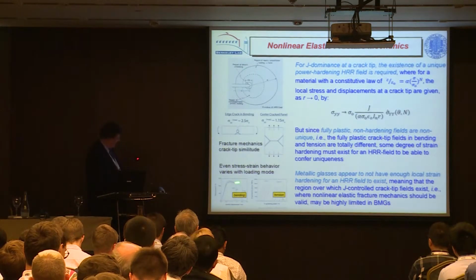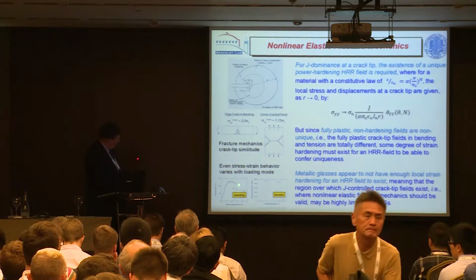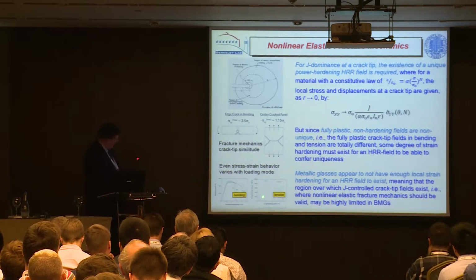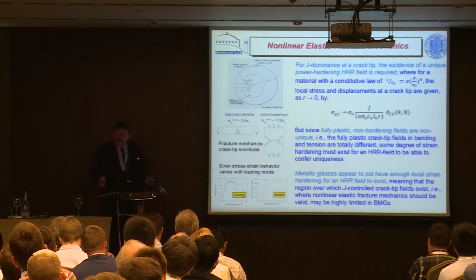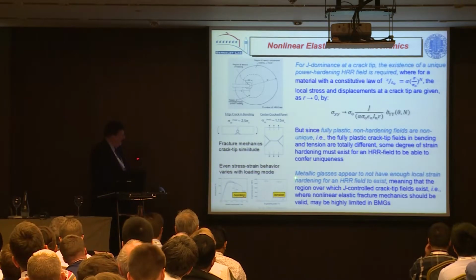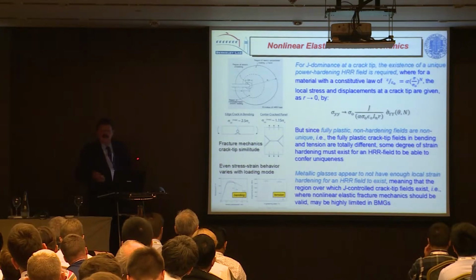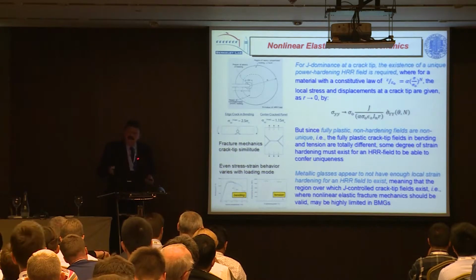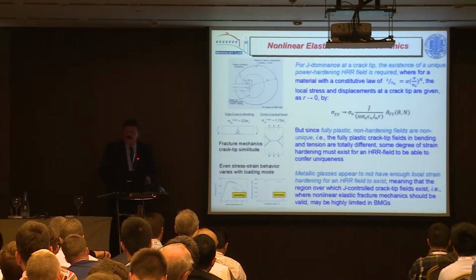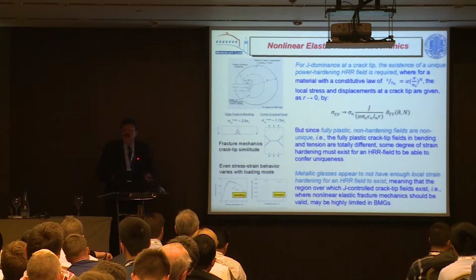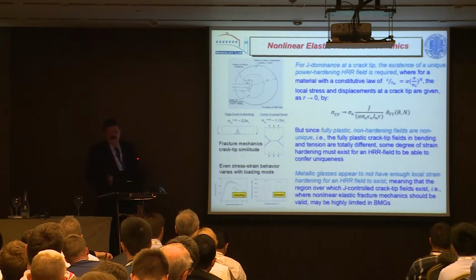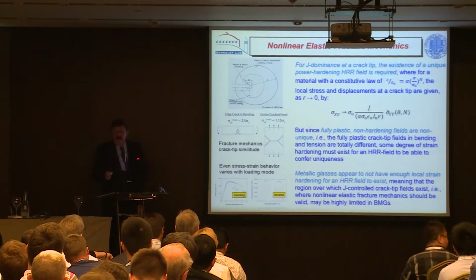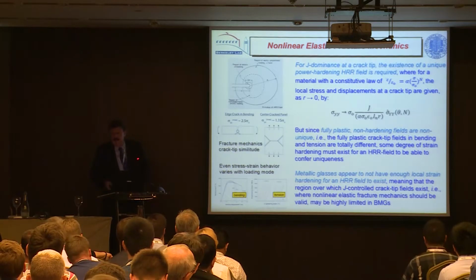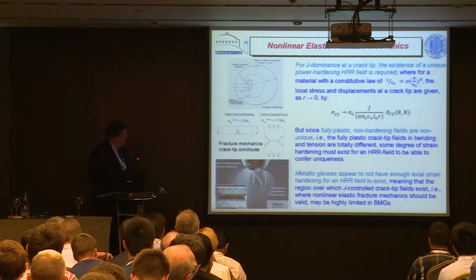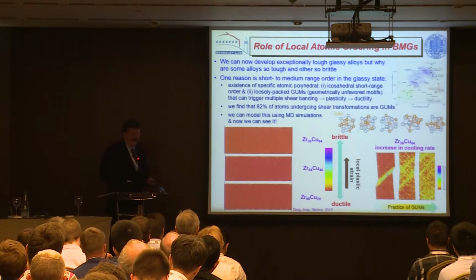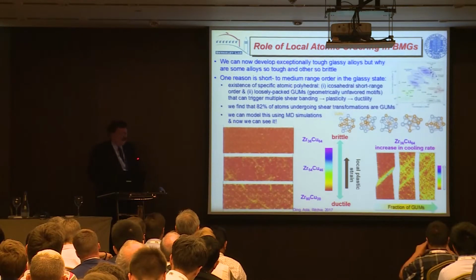Even tensile tests in these glasses are very different. This one is for bending, this is one for tension. So we think that basically it's going to be very difficult to get reproducible numbers in metallic glasses once you get to tough glasses, because the range at which the J approach to nonlinear elastic fracture mechanics applies is very small, perhaps even non-existent.